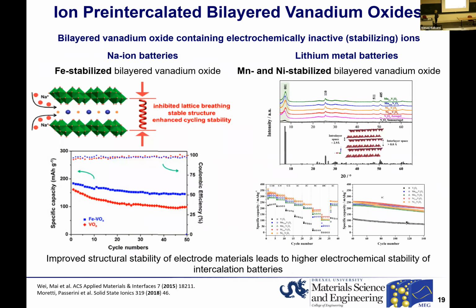All right, so the second direction with chemically pre-intercalated ions is stabilization. And again, this has been explored by other groups. Liang Mai chemically pre-intercalated iron into bilayered vanadium oxide, and Stefano Passerini used manganese and nickel. And in both cases, they showed improved electrochemical stability when they cycled these chemically pre-intercalated materials compared to the pristine bilayered vanadium oxide that contained water only.